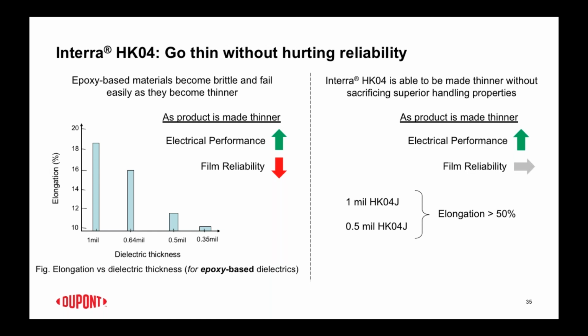A lot of people were reluctant going from 2 mil down to 1 mil when these products first came out. Then they realized the benefit of the 1 mil versus the 2 mil FR4s, and now we're getting people to see, well, if I go even thinner yet, you get the curve I showed earlier showing thinner is better as far as decoupling and lowering the inductance of the system, that people are now looking at the 12 micron version, and in some cases even going thinner.